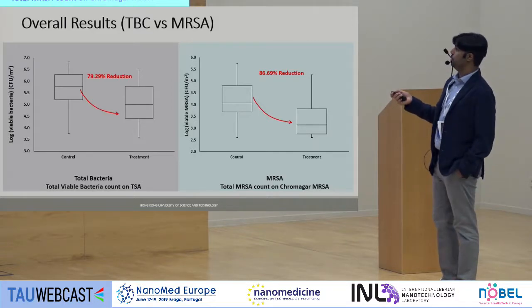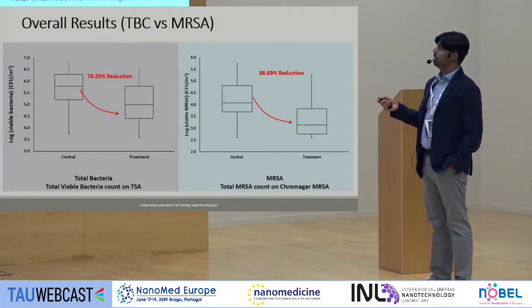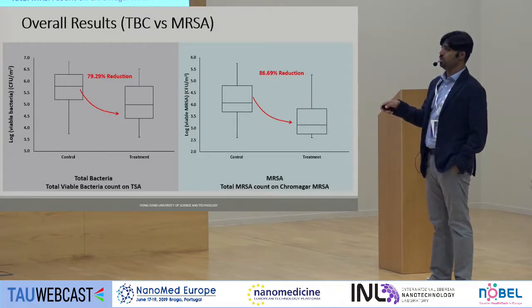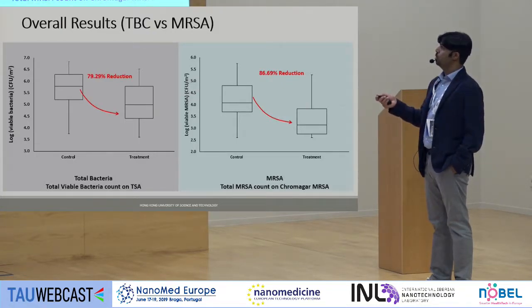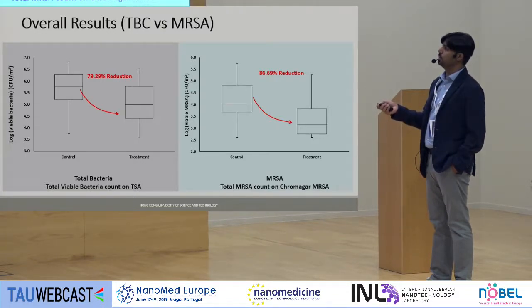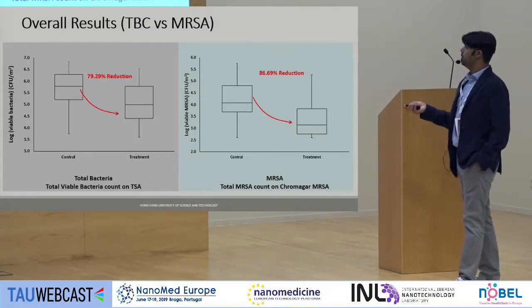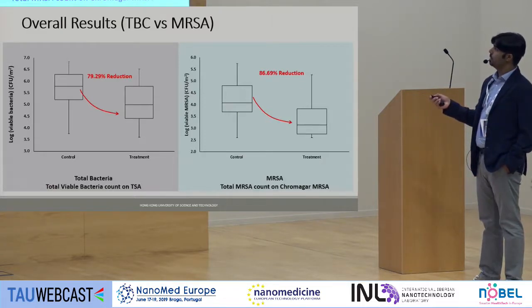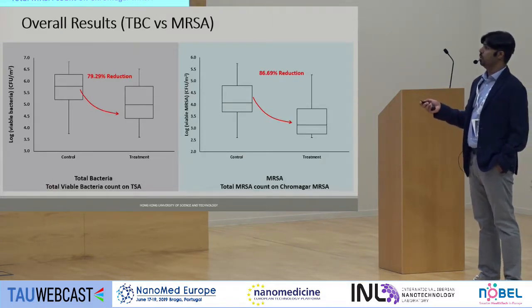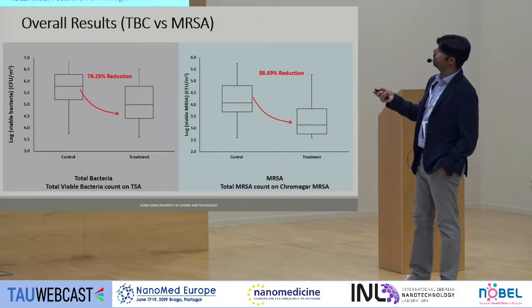So we'd like to share the results for total bacteria count without any discrimination of resistant strain or not. We found around 80% reduction from control to treatment. And this was the result for total bacteria. And on MRSA, we found around 86, 87% reduction. So it was around more than 1 log.